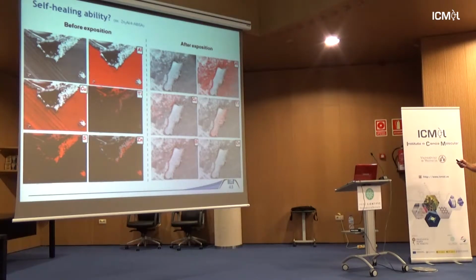And after immersion, you can see that if you look at the sulfur and zinc, they are more spread onto the surface here. It's the pink or red dots, protecting the copper and aluminum. So it means that there is really a migration of the zinc and the L-cysteine on the bare aluminum substrate.